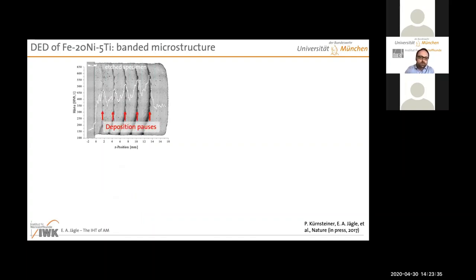Okay, so the key to understand why we have this funny layer-like behavior, and when I say layer, I don't mean a single layer of deposition, right? Because between dark layer to dark layer, there are 6 deposited layers. And we only understood this when we went back to the lab books of the students who did this deposition, and they wrote down, we made a pause after every 6th layer.